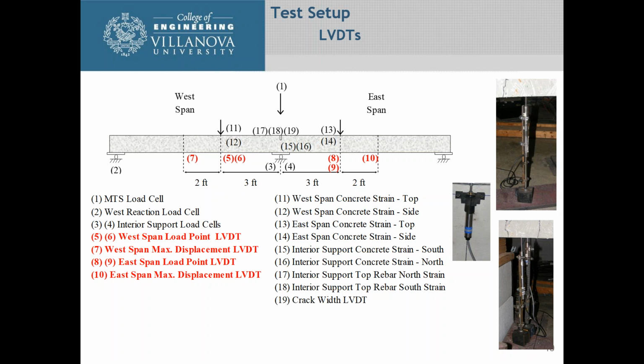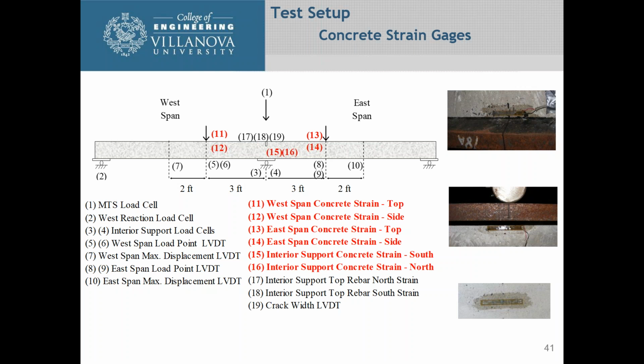We also put LVDTs at 7 and 10, and these were the points where we anticipated the maximum deflections based on our analysis. And the next thing we did is we had concrete strain gauges placed at various locations. We put concrete strain gauges on the sides of the concrete at the bottom, at the center support, and then put concrete strain gauges on top and on the sides at the points where we were applying the load.